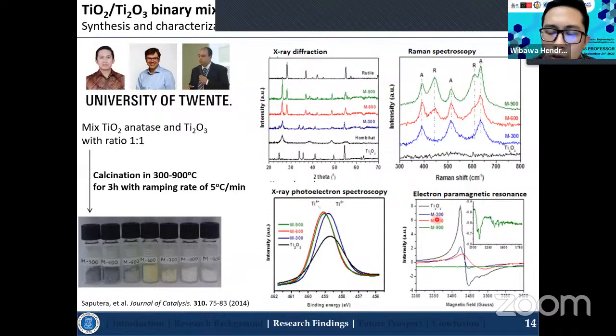And we also investigate the appearance of the titanium 3+ in the bulk structure of the TiO2 by using the electron paramagnetic resonance. It can be seen that at 600 degrees C and also 300 degrees C, the titanium 3+ appeared, which indicates that the generation of titanium 3+ is successfully done in this type of catalyst, which can later be very beneficial to improve the adsorption efficiency and can also be activated under visible light absorption.